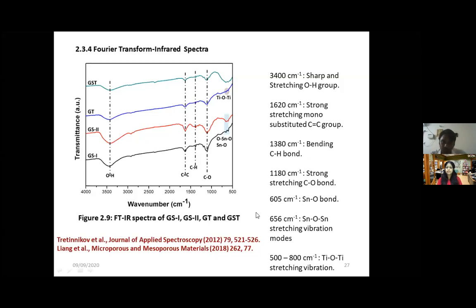So even we have a lookup table for this. For all the 4 sensors, from 3400 to 1180, we have common peaks that have been attributed to the hydroxyl functional group and the C double bond C functional group. These functional groups are necessary for the acetone to get chemisorbed.